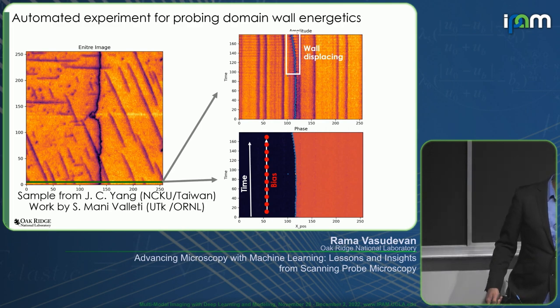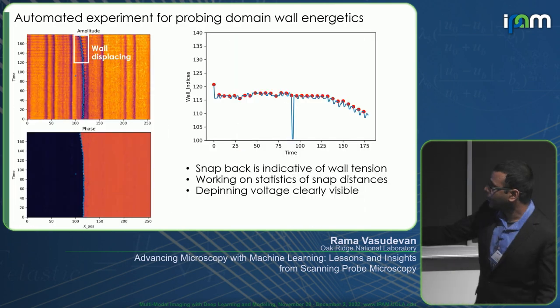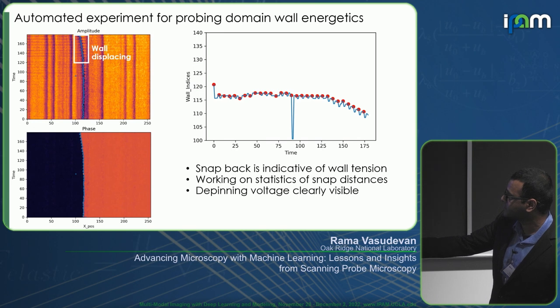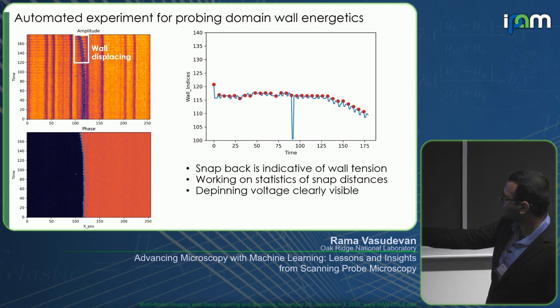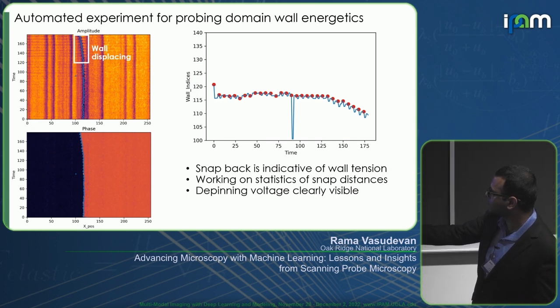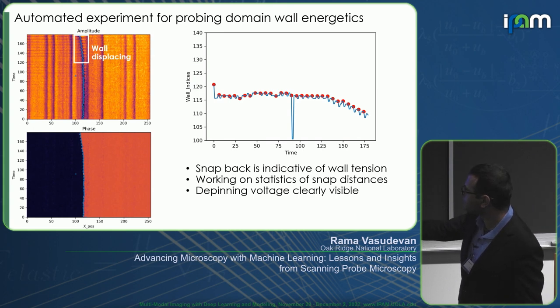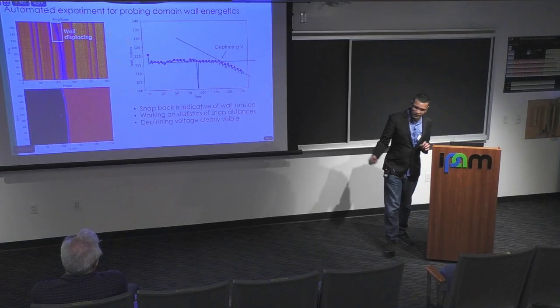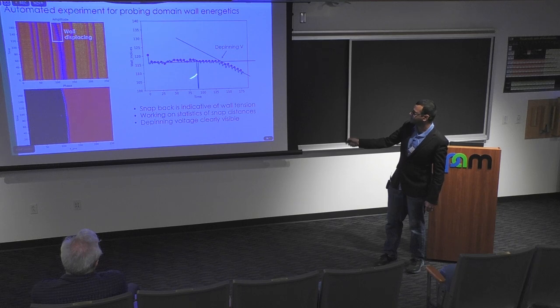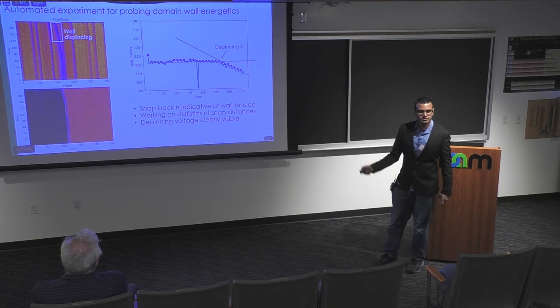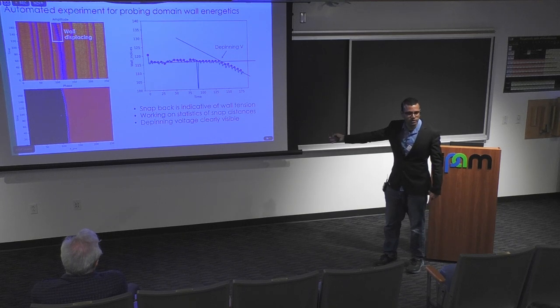I'll show you what that looks like if we fit Gaussians to find the actual position of the domain wall in this experiment. You can see that initially it's sort of flat. Nothing much happens because the wall is not responding to the fields that we're applying. It's too small. But after a particular threshold is reached, the wall starts to move. And so you can very quickly determine what this depinning voltage is, and we can map this depinning voltage across the entire sample in a completely automated manner.